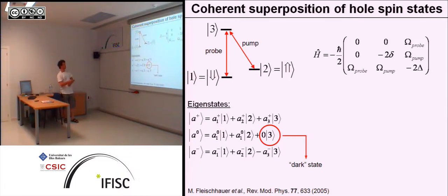And coherent population trapping now refers to this lambda system. We have the two ground states, so hole spin down and hole spin up, and we couple them to the same common excited state. And this is now basically this lambda mechanism. And because they couple directly between these three without a fourth state involved, this whole process is coherent besides the dephasing of the individual states.